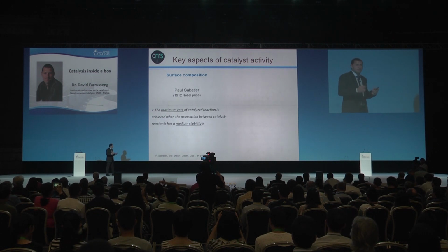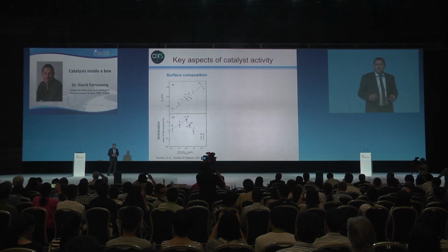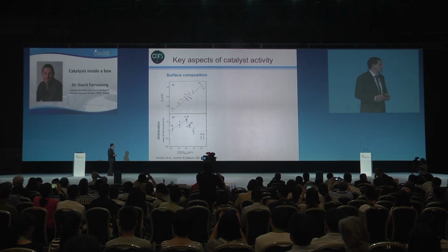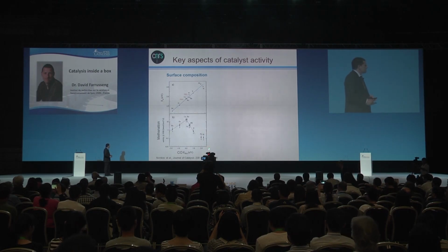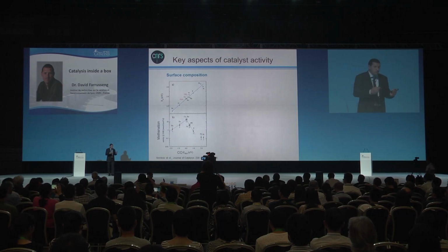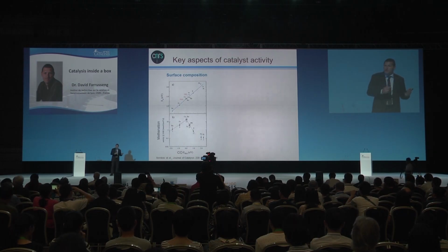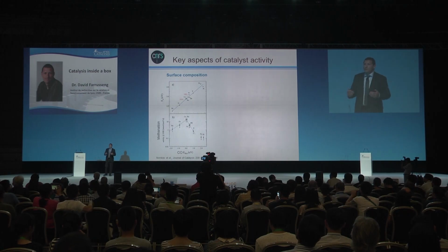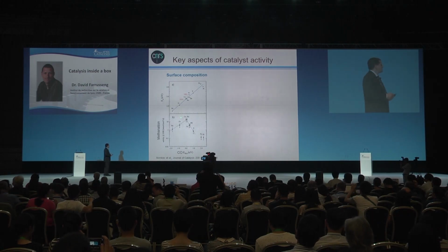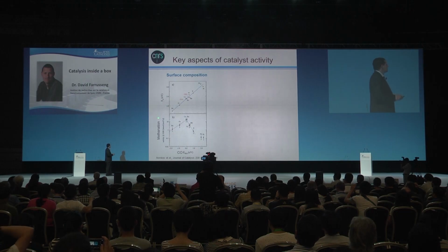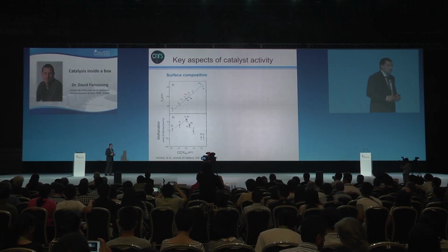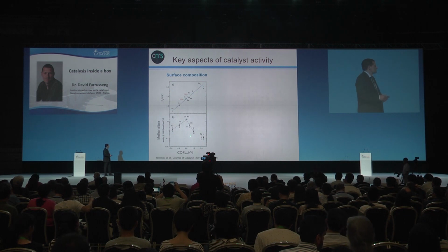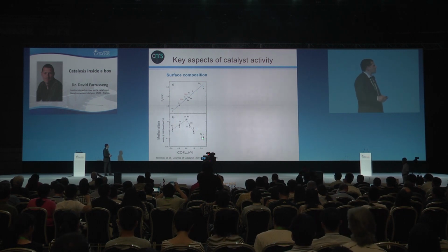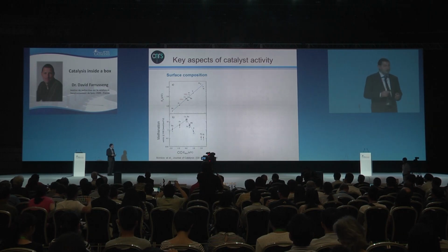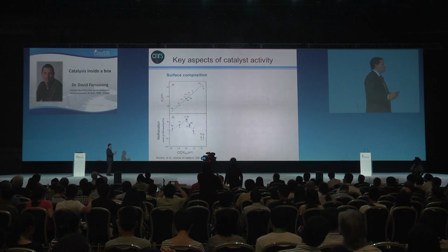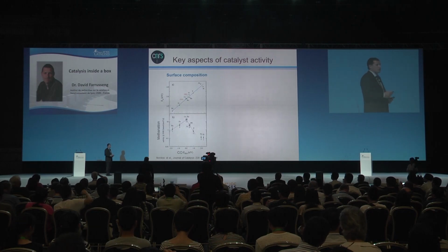This principle has been put into kinetic expressions later on, and the strength of adsorption between the reactants and the surface can now be computed or described by DFT. Here is an example of a reaction of methanation of CO. I will not go into the detail of that, but basically what it says is that for palladium and platinum, with very weak energy of dissociation, the reaction rate of methanation is low. And on the other hand, for ruthenium or iron,